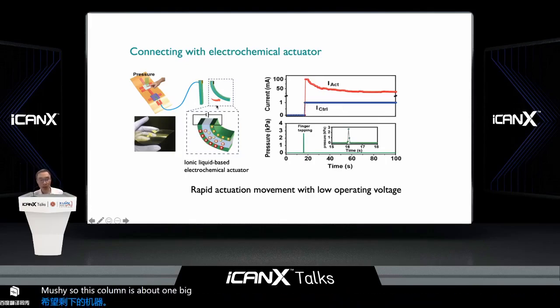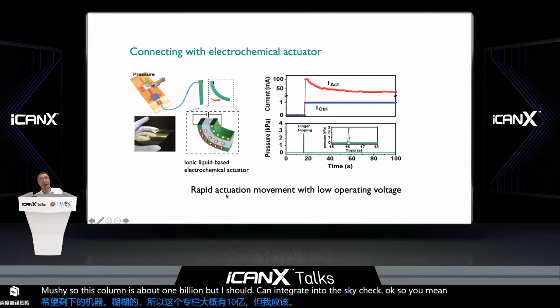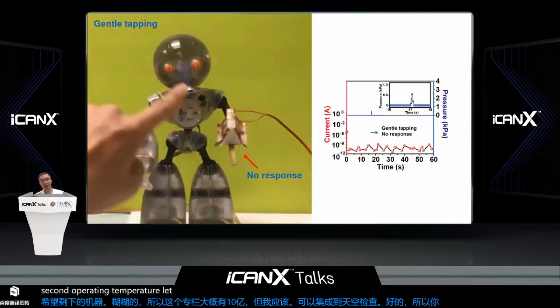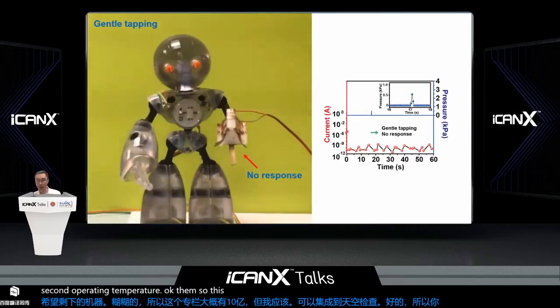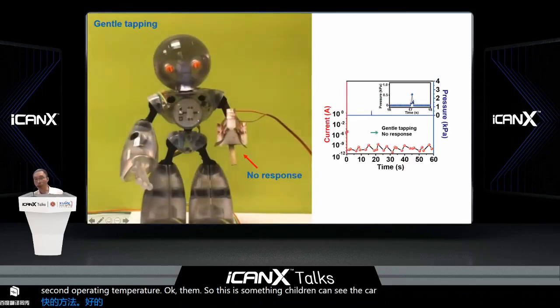But in the actuator area, in the component, the current can be more than 100 milliampere. Then the ions can integrate into the electrode and switch the device on. So it has a very fast activation movement, less than a millisecond, with low operating voltage. Let me give you a demo. This is a gentle pattern with low force. You can see the current is very low, the pressure is less than 1,000 Pascal.